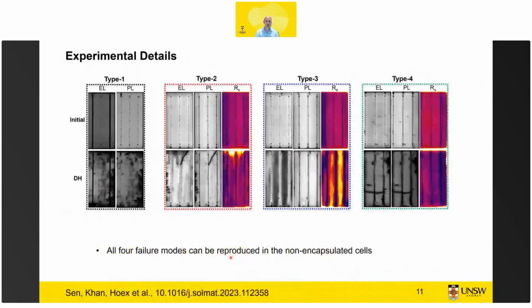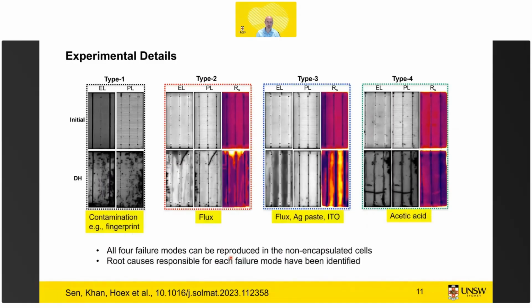The good thing was that we were able to reproduce all of these failure modes at the cell level. And this is important to repeat based on our earlier webinar, because this cell level testing is a lot quicker. It's typically 1 day. And we know how we stress the wafer, so that really gives us insight into the failure mode, and we can do a lot of advanced analysis.